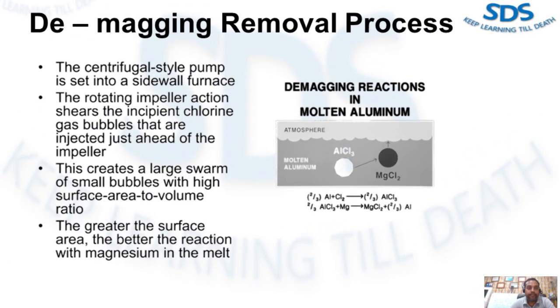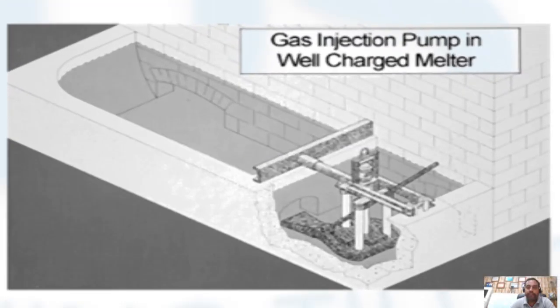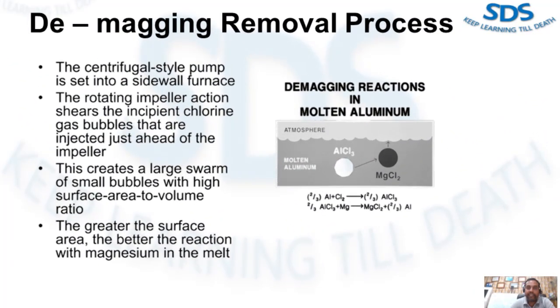Okay, now let's discuss the demagging removal process. The centrifugal style pump is set into a sidewall of the furnace, as you can see in this figure. The action of the rotating impeller, at 300 to 800 rpm, shears the incipient chlorine gas bubbles that are injected through the lance just ahead of the impeller. This creates a large swarm of very fine bubbles with a high surface area to volume ratio. The greater the surface area, the better the reaction with magnesium in the melt. You can see this process in this image.